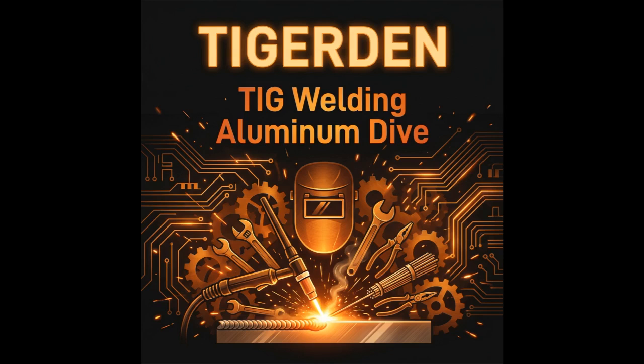So that's why we use alternating current, right? The AC flip-flop? Exactly. We're essentially using the positive side of the AC cycle to blast that oxide skin off like a pressure washer, and the negative side to actually shove the heat into the metal. If you don't get that balance right, you're either not cleaning the surface and getting puddle pepper, those little black specks, or you're overheating your tungsten until it looks like a burnt matchstick.